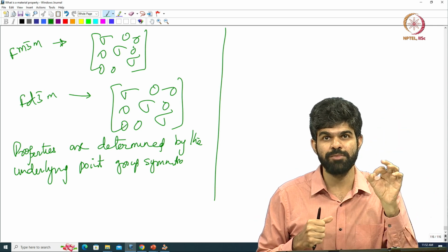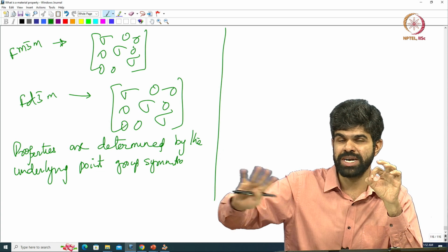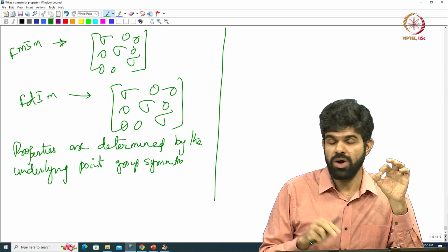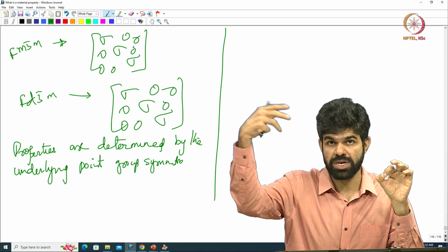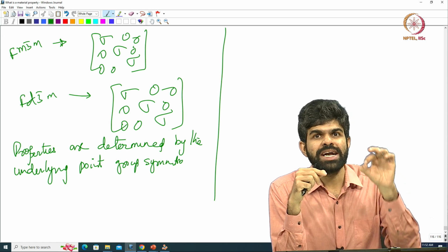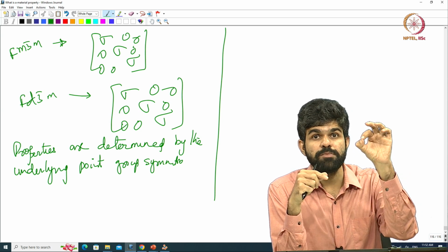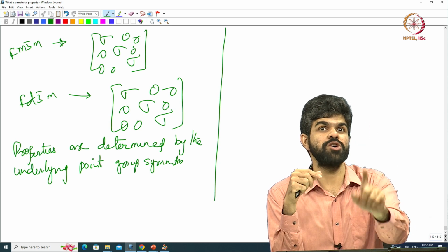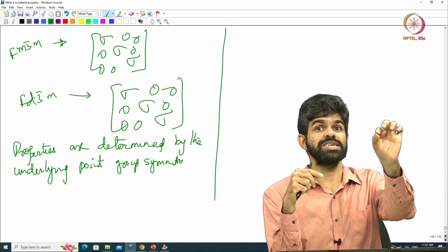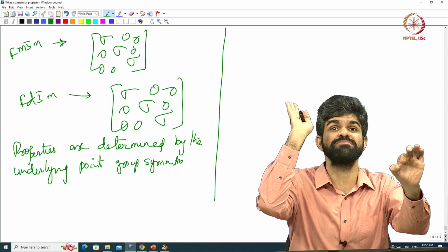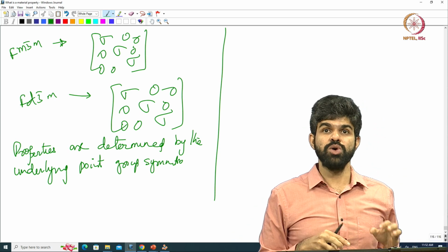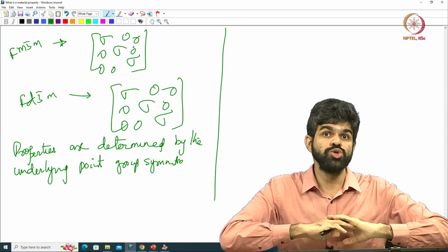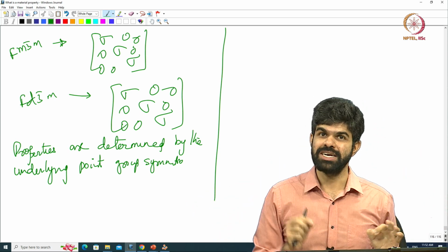The underlying point group is obtained by removing all translational vectors in the glide or screw operations, and the properties of the crystal follow that symmetry. For all practical purposes, that symmetry does exist, even though there is no point in the crystal which has that symmetry.